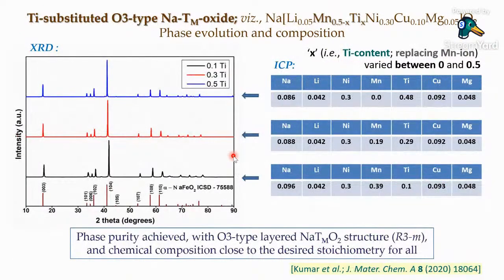Now, we wanted to start by addressing the air-water instability, and we selected an O3 type composition, and you can see there are a lot of substitutions in the transition metal layer, primarily to suppress the phase transformations that take place during the sodium ion insertion and removal.